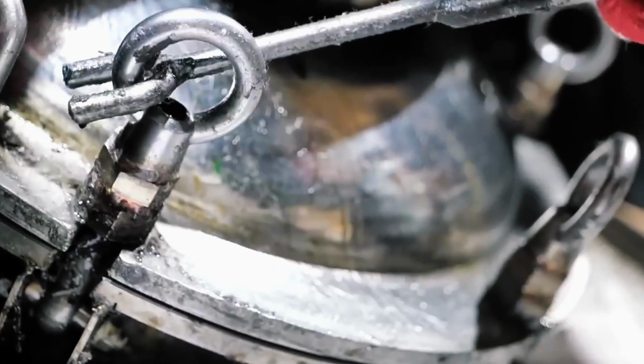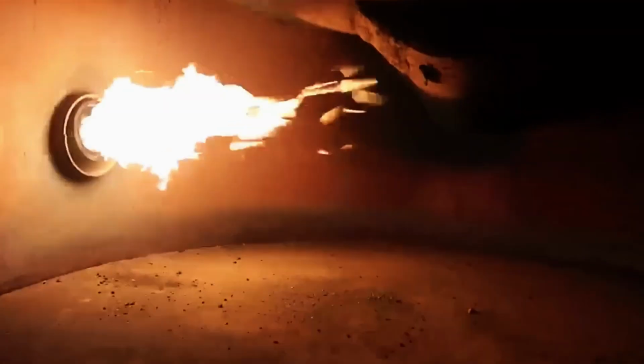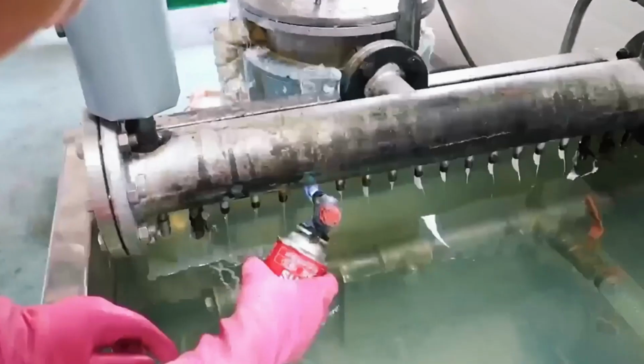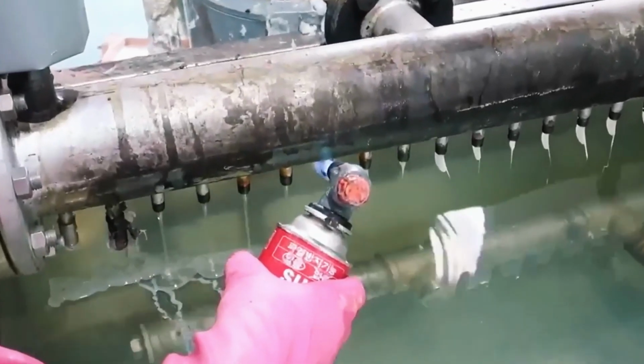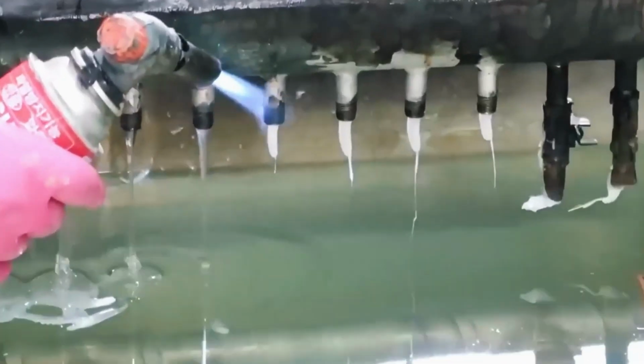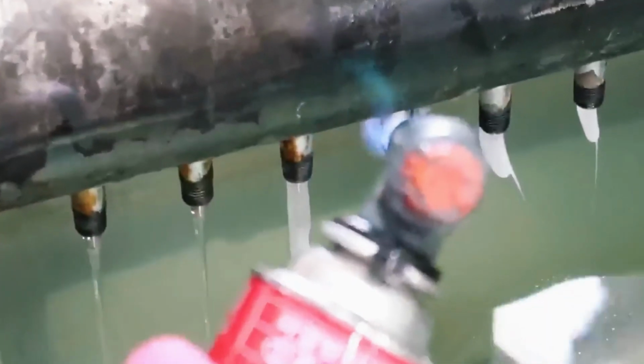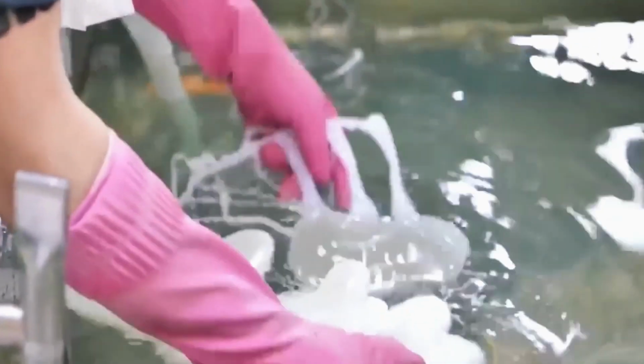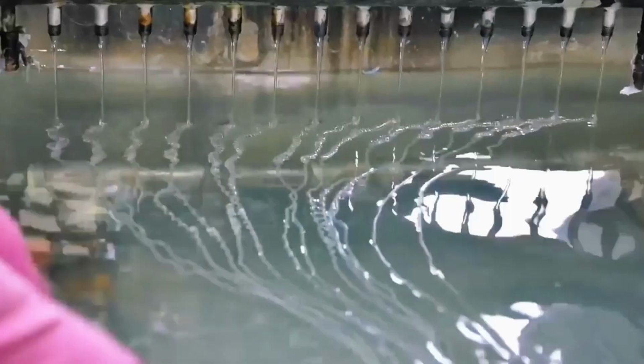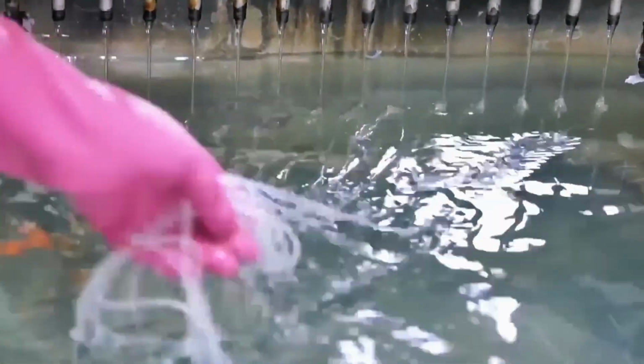It is dispersed using high shear agitators, spinning at speeds close to 10,000 revolutions per minute, like industrial blenders capable of breaking down any clump. The result is a thick gel that does not drip, ideal for applications on vertical surfaces or for filling gaps, something a pure liquid could not achieve. This practical detail makes it possible, for example, to repair cracked ceramics or splintered wood without the adhesive sliding out